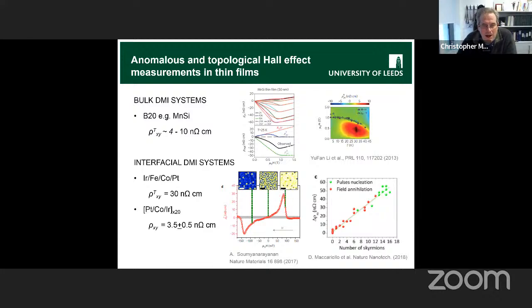This one is from a quite large group that was led by Christos Panagopoulos in Singapore. They did MFM imaging, and they also measured the Hall signal, subtracted off all the other bits, and they see these excursions around the fields where they're seeing Skyrmions, and they got a few tens of nano-ohm centimeters of Hall signal here.